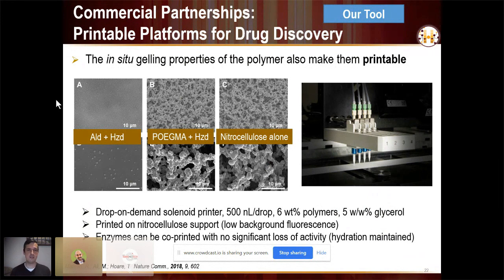What you can see in the image is if we just print non-cross-linkable hydrogels, they rinse right off the paper. But if we sequentially print our aldehyde and then hydrazide polymer, you don't see that bumpy morphology in nitrocellulose anymore. We've created a gel layer on the surface. We also showed that enzymes can be co-printed without any significant loss of activity. And interestingly, this can be just sitting on the bench at room temperature, we've tracked up to 3 months, where there's no significant activity loss. And we think this is just because these hydrogels are very, very water binding. It keeps that hydrated environment around the enzyme.